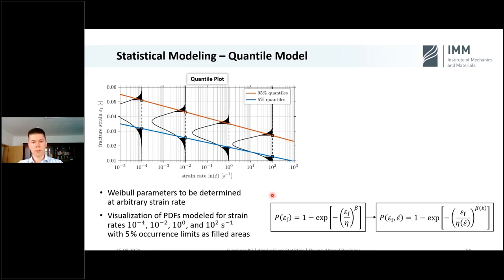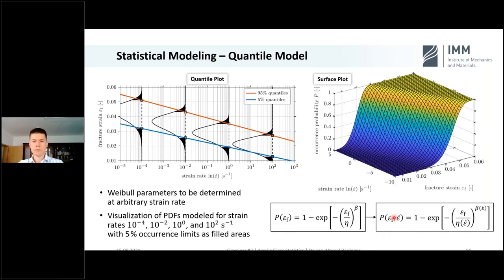And that allows us to really go at each arbitrary position and define our two-parameter Weibull distribution. Here shown in the equation again, that is the common definition of the Weibull distribution. And we can say now that our occurrence probability is, in addition to the fracture strain, dependent on the strain rate. And that gives us a three-dimensional dependency we can nicely show in this surface plot. Here we have our fracture strain, the strain rate, and both define our occurrence probability.